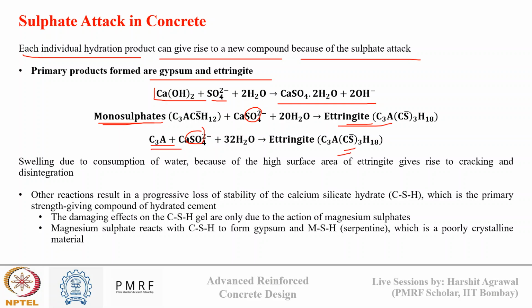Okay, now if you see in the second and the third reaction, the reaction consumes a lot of water, 20 moles and 32 moles of water. And due to this consumption of water, there is swelling in the hydration products that are forming. This leads to high surface area of the hydration products, in this case ettringite, which leads to cracking and disintegration in concrete.